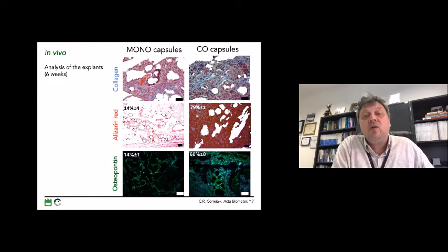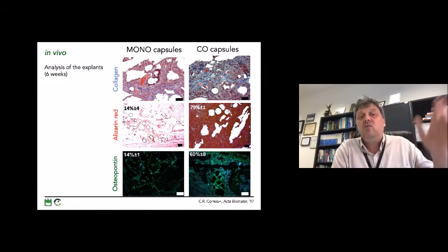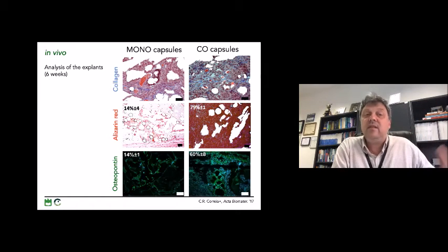In the monoculture, we could not see too much collagen formed, neither the presence of calcium nor osteopontin. In contrast, in the co-culture conditions, more collagen could be seen. Massive calcification was produced by the human cells in the place where there is no bone. So this is really calcification provoked by the human cells, and also much more osteopontin. So this is really an indication that the cellular ingredients can be very important to generate the intended tissue that we want to engineer.